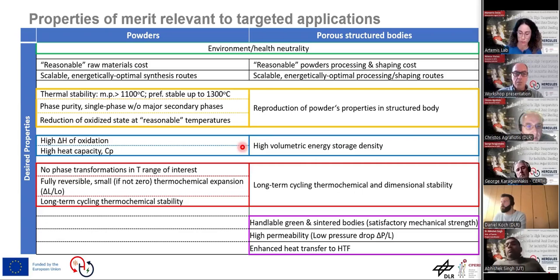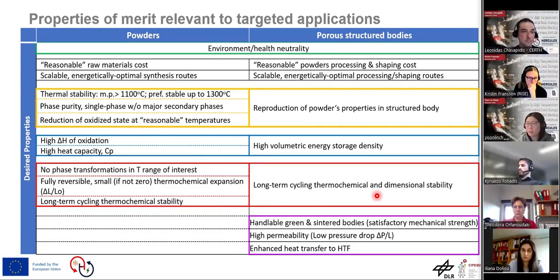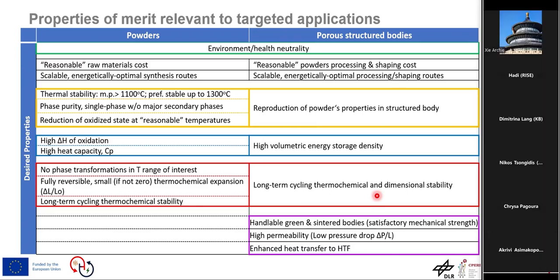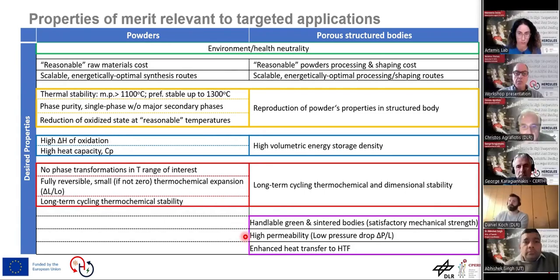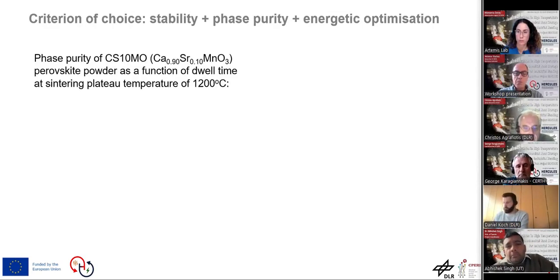And as we said before, we don't want these compositions to have any phase transformation in the range of interest. Because we cycle them from ambient to high temperatures, they will suffer some expansion and contraction, not only thermal but thermochemical, but we want this to be reversible and small if non-zero, and all these materials and shaped bodies to have thermomechanical and dimensional stability so that they don't crack or collapse under this cycling. Of course, we need both the green and the sintered bodies to be handleable, to have mechanical strength at a satisfactory level, and high permeability in order for the hot air and cold air to flow through them. That's why we investigate other porous structures to enhance the heat transfer to the heat transfer fluid. So these are the criteria that we screen our materials by as we go along this value chain process. And if we click, I will show some representative tests with respect to such properties that we use to screen our materials.